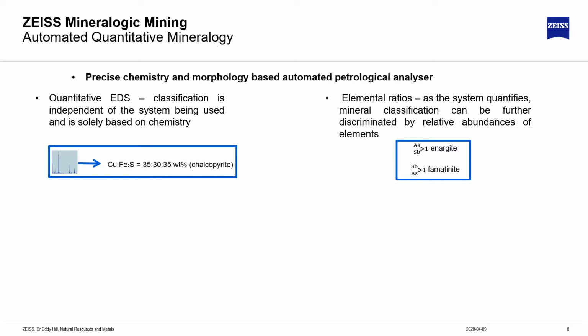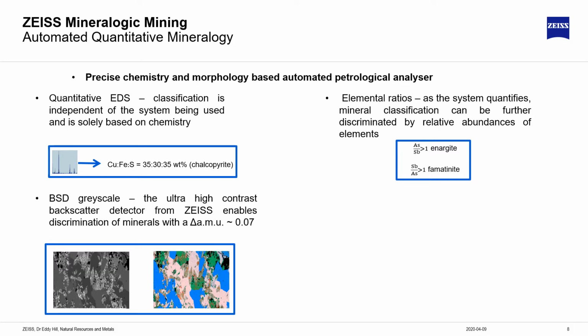Since we have a chemical composition, we can then assign elemental ratios to that classification to further tighten the discrimination of the phases being analyzed. We can also make maximum use of all of the detectors on the SEM. And in the case of the grayscale produced by the backscatter detector, we can add this to the classification library. And so we can discern between phases that may have a similar chemistry, but may be a hydrous phase.